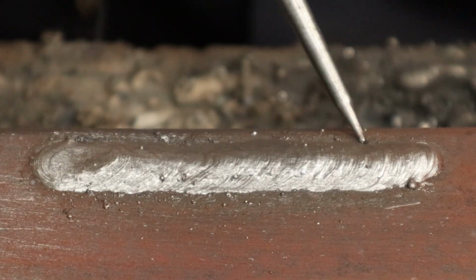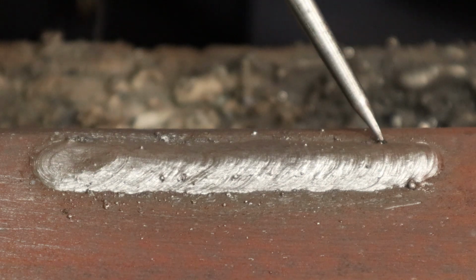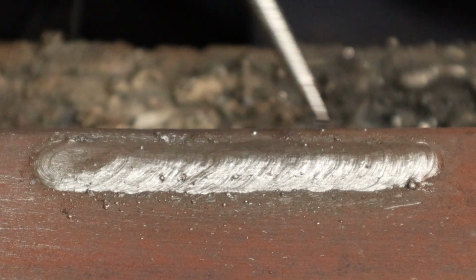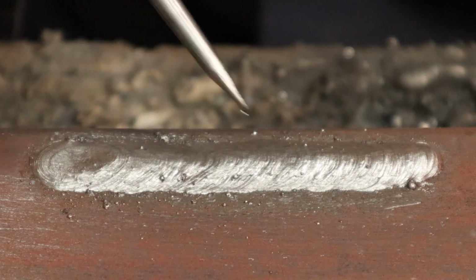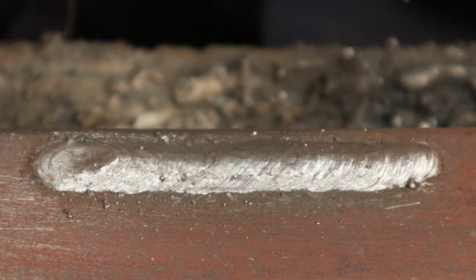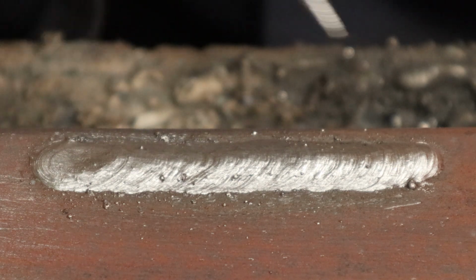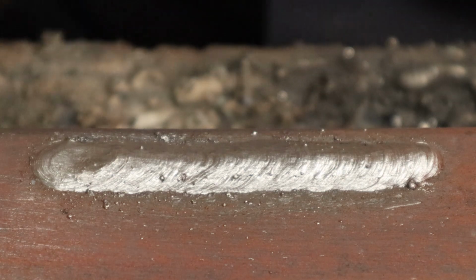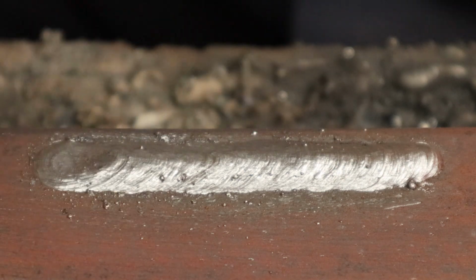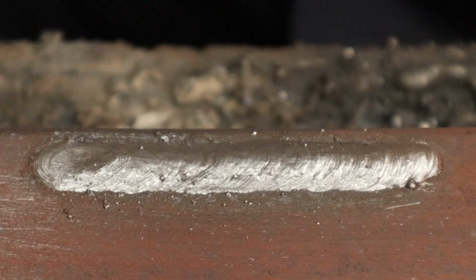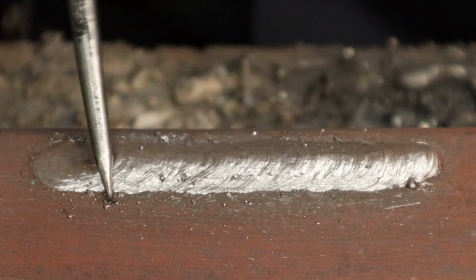And then as for heat and penetration, the weld bead isn't sitting up high and looking like a worm or bird poop on top, so it doesn't have any undercuts. So it was hot enough, yet not so hot that it was actually flat and a super wide weld bead and maybe even concave as it started to sink through this. So overall, not a bad weld.